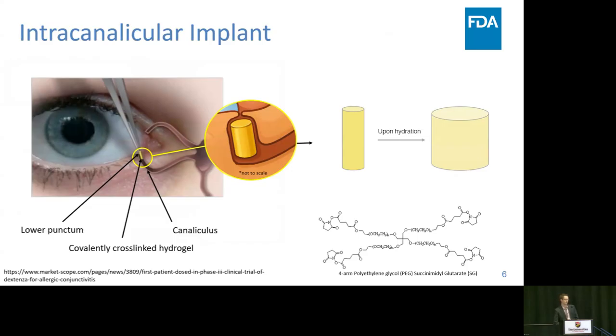This particular product is a dexamethasone intracanalicular implant. As you can see in the diagram on the left, these are placed through the lower punctum, which is about a 0.5 millimeter wide opening near the inner part of the eye. And this goes into the canaliculus, which is basically the tear duct. And it sits in the vertical part of the canaliculus there, and it swells to expand and then fit snugly in place to remain there as a punctum plug. And it remains swollen and gradually releases the entrapped drug API, in the case that we're going to be talking about dexamethasone, which is poorly water soluble. So this leads to extended prolonged release duration.